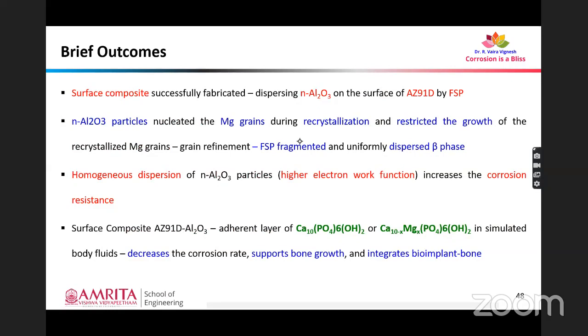We have fabricated a composite by dispersing nanophase alumina on the surface of AZ91D by friction stir processing. The nanophase alumina particles nucleated magnesium grains during recrystallization, and restricted the growth of recrystallized magnesium grains. And that resulted in grain refinement. Added to that, friction stir processing has fragmented and uniformly dispersed the beta phase. So this cumulative effect and the homogeneous dispersion of particles resulted in high hardness in the stir zone, and the homogeneous dispersion of nanophase alumina that has high electron work function increases the corrosion resistance of the material too.